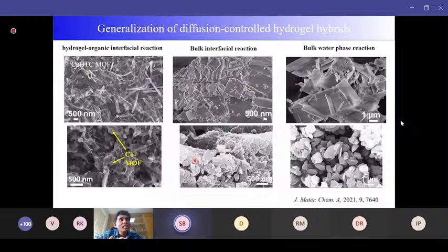And not only this structure, I would like to introduce this also: using the graphene hydrogel as an interfacial reaction media is not only limited to polyaniline, but can be extended to any nanomaterial growth. For example, we have tried a variety of materials, such as copper-based metal organic frameworks. You see that whenever we use the hydrogel organic interfacial reaction, it gives rise to nanobelt structures connected with the graphene, whereas in the bulk reaction, when there is no graphene hydrogel, it leads to random or bigger structures.